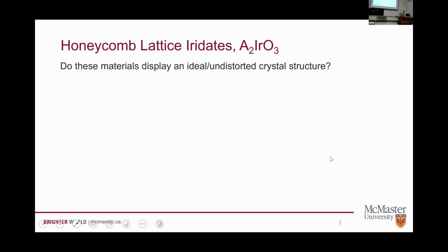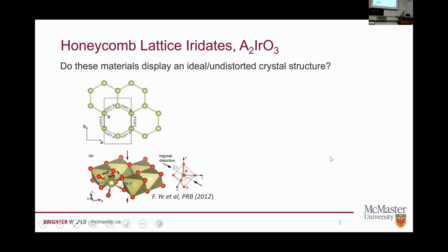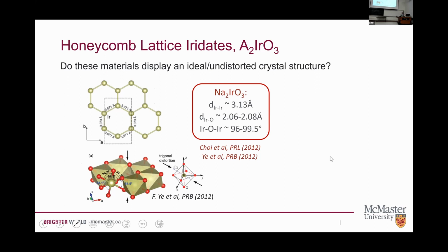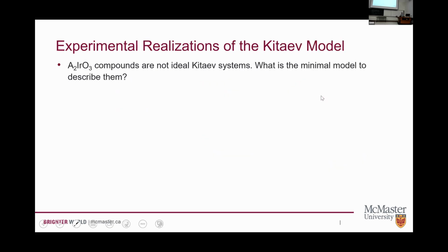The other thing we can do is look at the crystal structure to see if we're really close to this perfect 90-degree bond angle. And it turns out that we're a little bit off here as well. So the iridium honeycomb lattice is nice and regular. We get sort of 3 angstrom bonds all the way around here. But there's some distortion to our iridium O6 octahedra. And as a result, the bond angles here are off by somewhere between 3 and 10 degrees, depending on whether we're looking at the sodium or the lithium version of these compounds. Okay, so we know that we don't have an ideal Kitaev material, but maybe there's still Kitaev physics in here if we can find it.